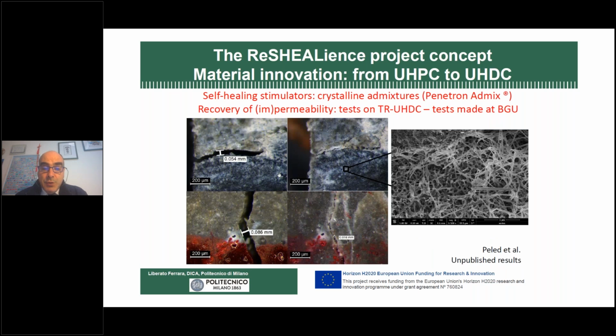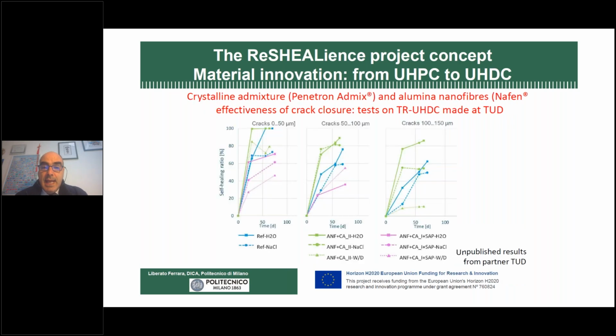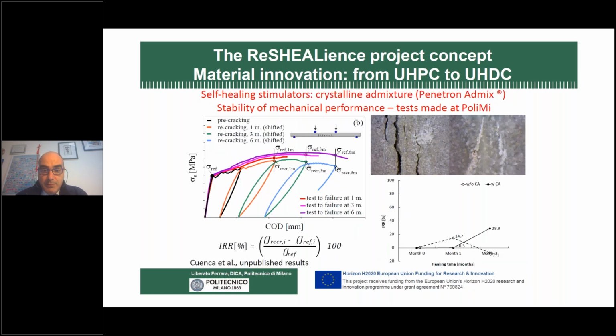And you can see here some visual images of the crystalline growth in the cracks, which are completely closed. The comparison of the technology that we have used in our project, the green curves in these graphs, with other technologies to promote self-healing, for example the superabsorbent polymers, which are the purple curves, or the reference material, which are the blue curves. So in our case, it was always much better, also for large crack widths, more than 100 microns.